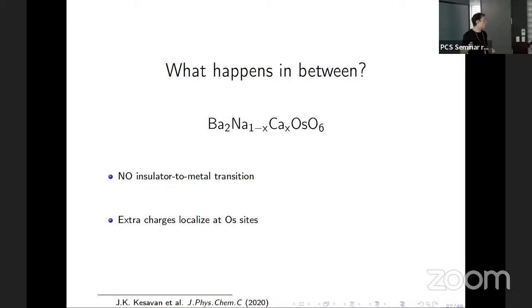It's always an insulator. And so the question that came up was, how is this possible? Usually, for example in an iridate, you dope with electrons and you get a metal. This is usually what happens. When you dope, it's really likely that at a certain concentration you have an insulator to metal transition. So the idea here was that the formation of polarons was hindering this transition.